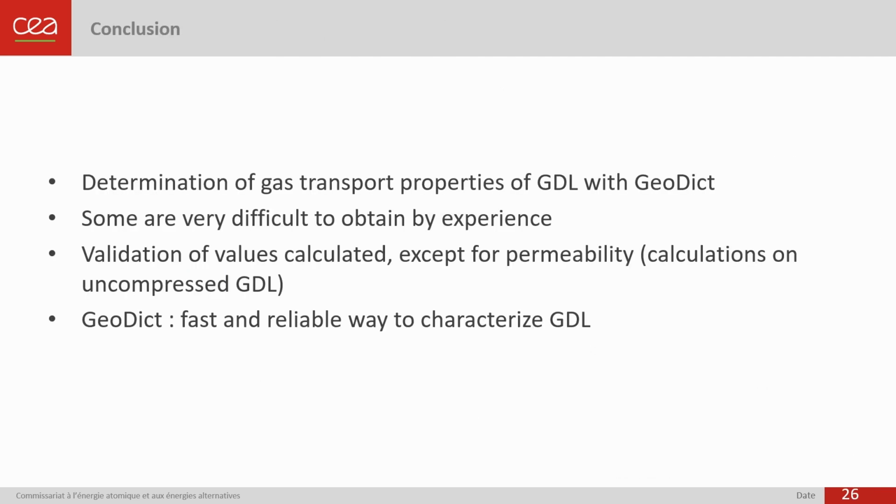So to conclude, I used GeoDict to determine gas transport properties of the gas diffusion layer. It helped me obtain some values which are very difficult to obtain by laboratory experiment, and some values could be validated, except for permeability, because calculations have been made on an uncompressed GDL, whereas most of the values obtained in the literature are for compressed GDL.